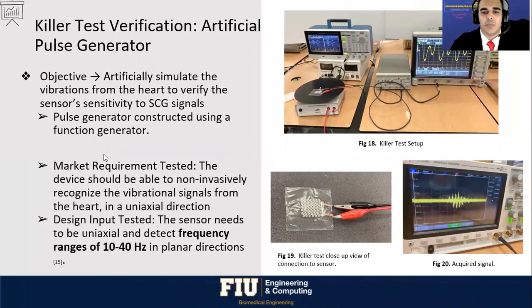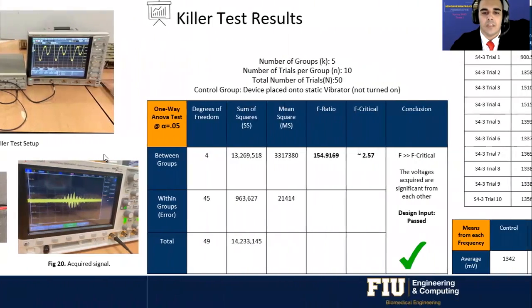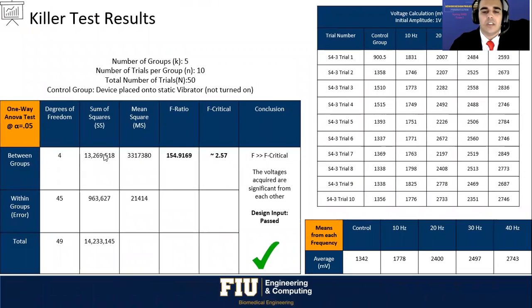The last but most important verification test was to determine if the device was able to sense standard SCG signals. To accomplish this, we used an artificial pulse generator to stimulate vibration to the device. We decided to use a one-way ANOVA analysis as we wanted to see if our sensor was capable of detecting and sensing these vibrations in relation to SCG frequencies. With confidence levels of 95%, it was determined that the voltages generated are very significant and ultimately passed the killer test.